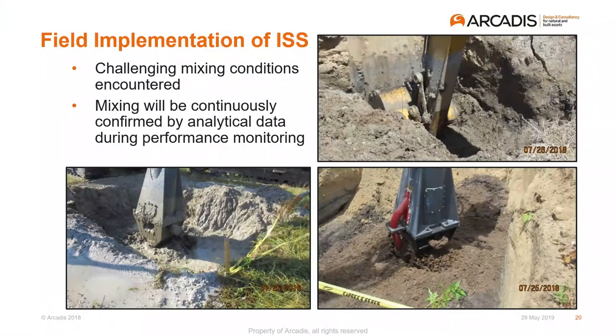We had challenging mixing. Anytime that you're going to implement an ISS, it's very important to make sure that you do a process pass. Process pass basically being that you just take an excavator arm and destroy the structure before you start adding in your fixant. We did not do that. We tried to do it all in one step. So we're going to be cognizant of that moving forward. But we did have some challenging mixing conditions, and it kind of played into the differences in Portland cement that we had to add.